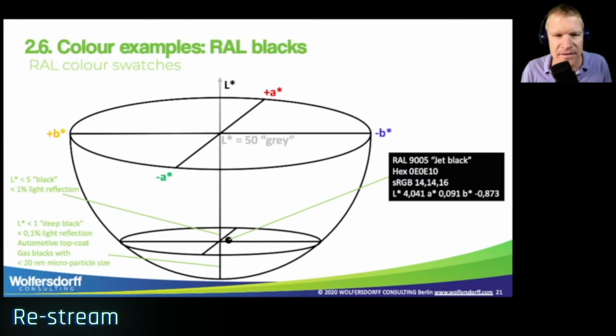And if we say L is smaller than 5, we can say we have less than 1% light reflection. Now, if the L star is lower than 1, we can say we have a deep black. We can have lower than 0.1% light reflection. This is the case for automotive top coat applications, and generally this deep black cannot be accomplished anymore by the standard furnace carbon black process, which makes all the rubber blacks and normal carbon blacks for plastic applications. But this is the gas black process, which produces very, very small particle sizes. We'll see later on in the presentation why this particle size is so important.